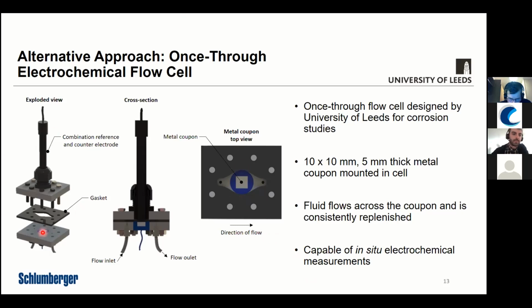So just to run through the main components of those, we've got two hard layers, if you like. They're polymer material. In this particular case, we've used an acid-resistant polymer so that we don't degrade the cell as we're running the experiments. And within those two layers, we house the electrodes for electrochemical measurements.